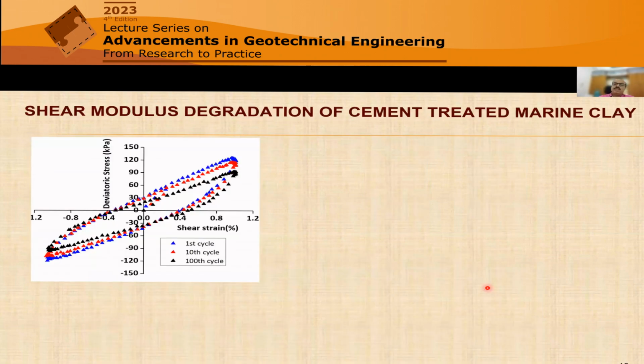Now we did the cyclic triaxial test on cement treated marine clay. We did it for a series of different conditions, but I'm just showing a typical one. As you can see, the blue line is for the first cycle, the red line is the 10th cycle, and the black line is the 100th cycle, and there is a gradual reduction of the shear modulus as the number of cycles progresses.